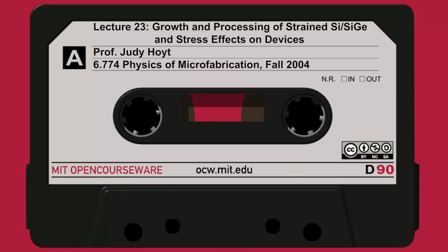If you grow the silicon germanium too hot, it turns out it doesn't even grow as a planar film. It grows as big little clumps, little mountains or islands. It doesn't wet the surface properly. And this type of growth mode is generally considered not very useful because it's not really a smooth film. So you cannot grow silicon germanium at too high a temperature for a given germanium fraction.